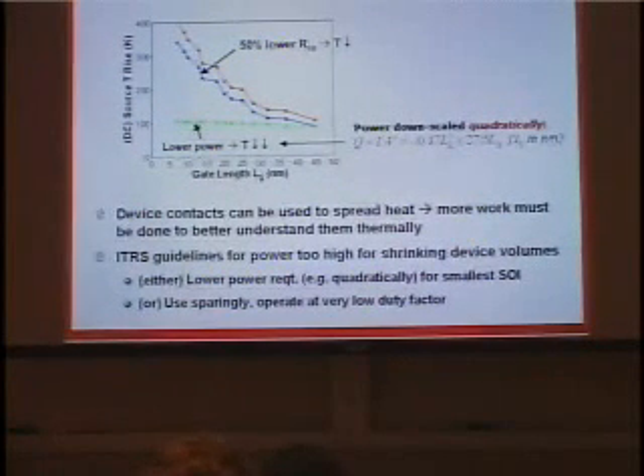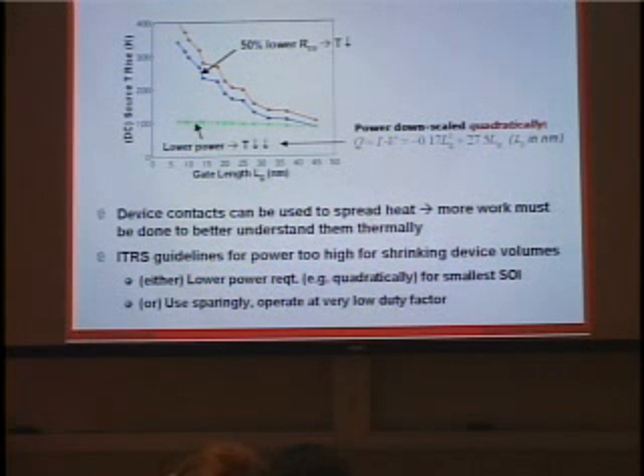There's very little understanding. This work is some of the first to go in that direction, but a lot more work needs to be done to understand these contacts, thermally speaking, as well as electrically. And then the other thing that we could do, of course, is get more power. The ITRS guidelines right now are actually too generous with the power. Remember, device areas and volumes are shrinking quadratically and cubically, respectively, with device channel length. I cannot put a constant amount of power in an infinitely shrinking device volume because I'm going to get infinite temperatures, obviously. So why don't I scale my power down quadratically as well? I use that simple formula, and it turns out that if I scale the power quadratically, I can keep the temperature essentially constant.